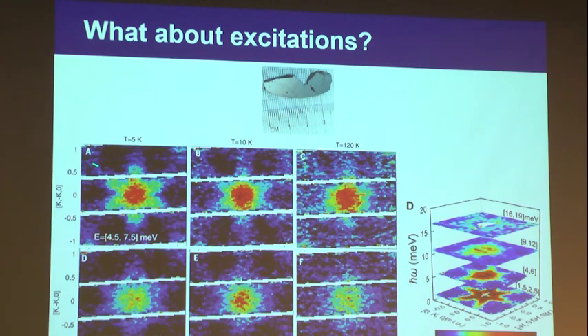At low energy, you have this kind of star-like excitation in reciprocal space. So this is inelastic neutron scattering intensity as a function of momentum in two dimensions. In this low energy sector, you have this star-like thing that's merging into more circular behavior up here. And if you increase the temperature, it's still there. So even if the magnetic order is gone, this excitation is closely related to the spin fluctuation that is inherent in the spin Hamiltonian of this system.